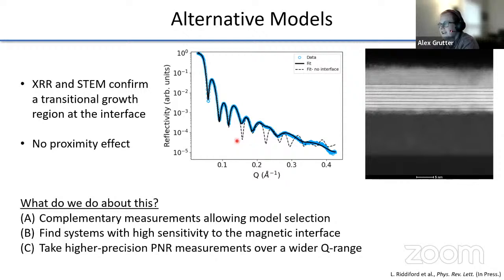So here in the dashed line, you have a proximity effect model, and in the black solid line here, you have a transitional growth region model. So that fits the X-ray reflectivity really well. And in the TEM, you can see a sort of subtle intermixed region of different quality right here that also agrees with this transitional growth region model.